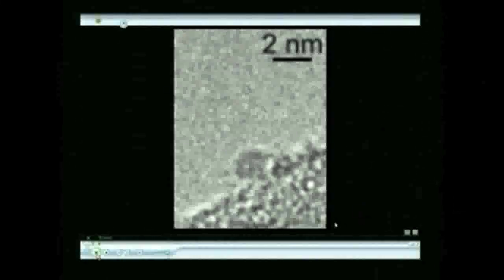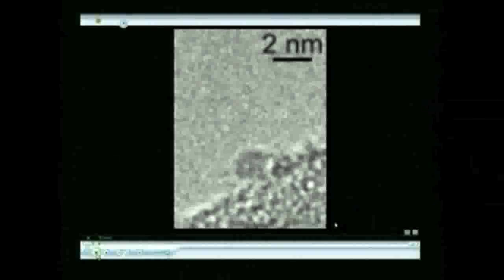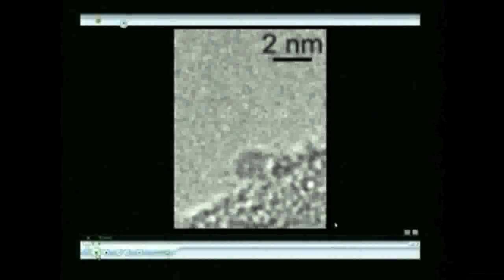This movie is done by TEM, Transmission Electron Microscopy. It's also called environmental TEM because in the environment, in the gas phase, some carbon molecules are put. In this case, this is acetylene, to be used as a carbon source. So in the gas phase, here are acetylene molecules. What you see is a metal particle, which is about 1.5 nanometers, and here is the support of the catalyst, which is in this case silicon oxide. We are now going to see what happens when you put acetylene in.